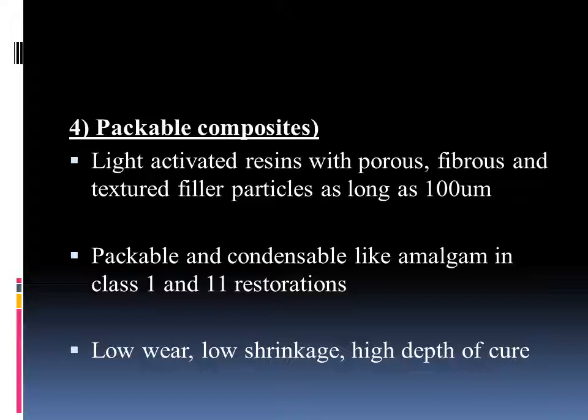Then the packable composites, as the name suggests, one of their applications is basically to be packed into the cavity. These are light activated resin with porous fibers and textured fillers. So over here we don't just have fillers, we have fibers as well, as long as 100 microns. So they're packable and condensable because of the fact that they have so much filler and fiber. The viscosity is very high, and that is why they're packable and condensable, just like amalgam, and they can easily be used in class 1 and class 2. They show low wear, low shrinkage, and they have a high depth of cure.